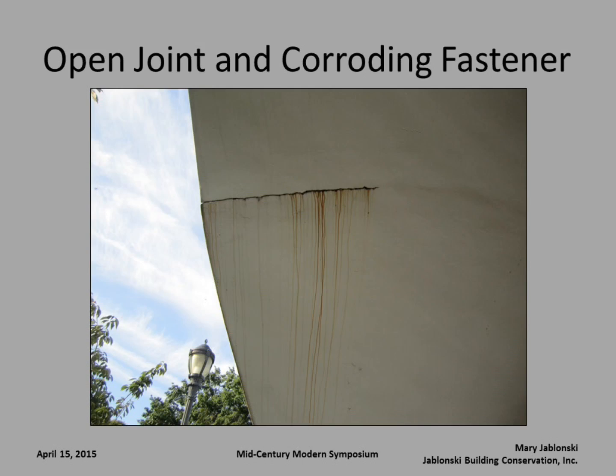But what's happened since they've moved the structural support of the infill panels of the glass and aluminum out, the wind loads, as you start getting storms and heavy winds, have actually caused these pavilions to move extensively, and you get the kind of cracking that you see here. And the other point to this cracking is you can see with the ferrous metal the corrosion staining coming out of the joints. The other thing you get is snow loads, which have not been as significant, I think, and we already heard from Nancy about the problems with foundations here, and so there is some settlement in this, which has also caused some cracking.